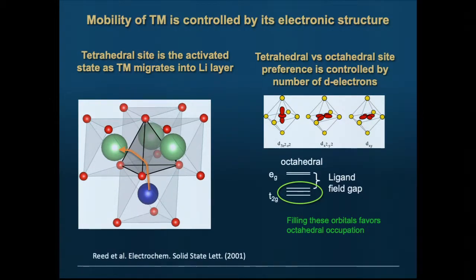Well, that depends on the electronic structure. Because a transition metal has 5 d orbitals, and in an octahedral environment they split, 3 down, 2 up, just because of crystal symmetry. These are called the t2g orbitals. These are the eg orbitals. And this is essentially the gap created by the octahedral coordination. So in basic, simple principles, what you want to do is fill these electron states, because then you will fully prefer octahedral coordination and not fill anything else.